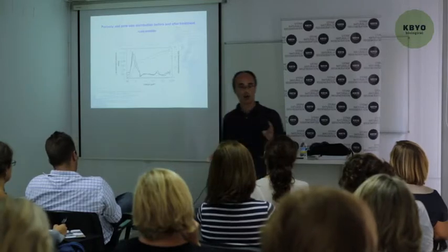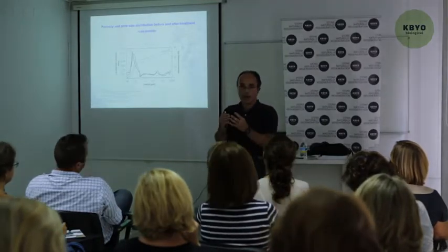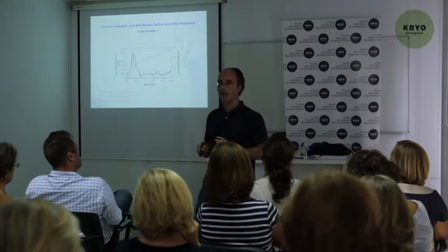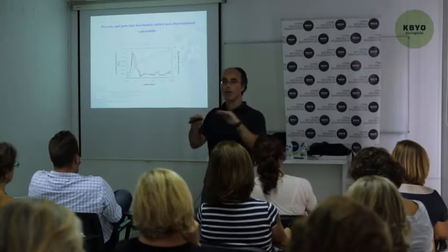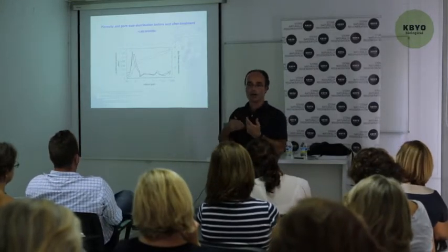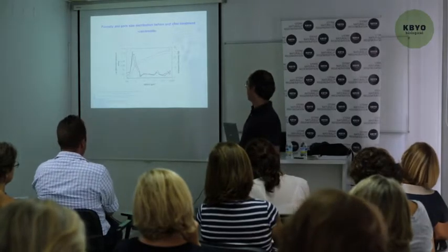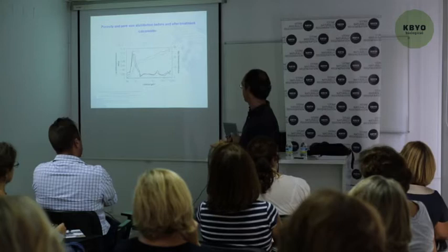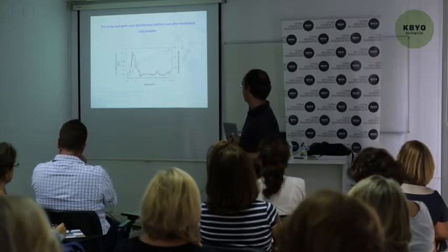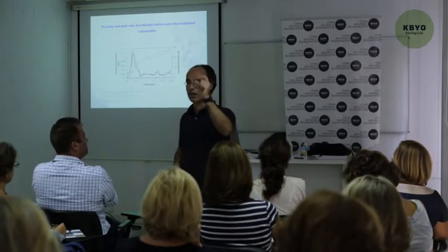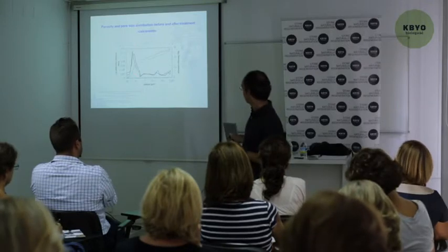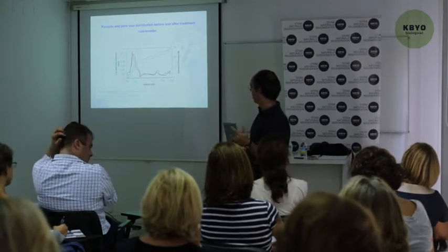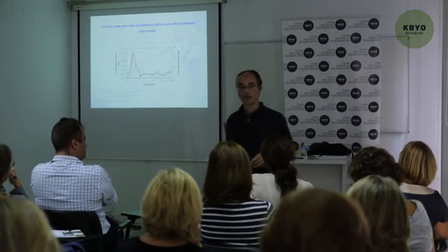So there is a reduction of porosity. This shouldn't happen. Pores shouldn't be plugged. By means of porosimetry and mercury injections, it has been proved that porous rocks with 29% of porosity reduce their porosity by 1% after the treatment. Regarding the pore size, notice in this distribution that the green and red curves are superposed. This means that there are no significant changes. They produce consolidation, but it doesn't obstruct the pores.